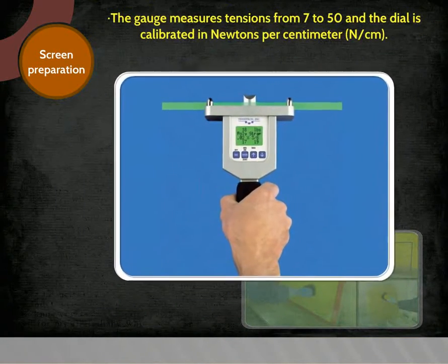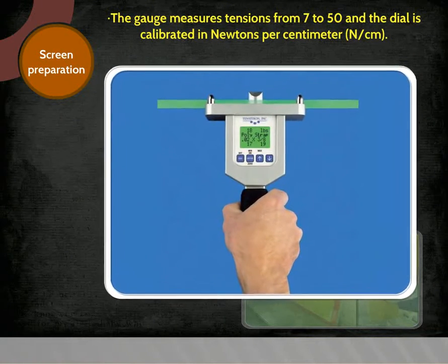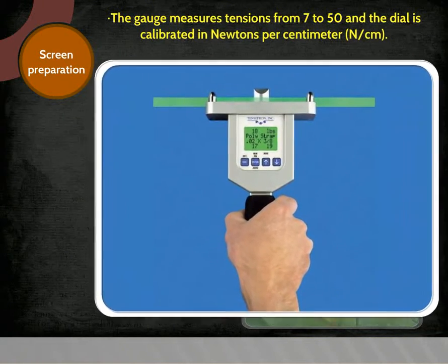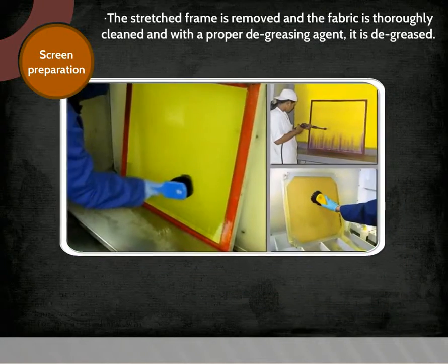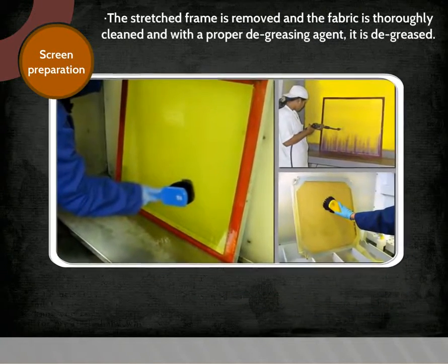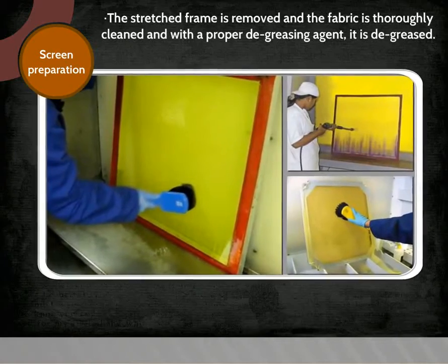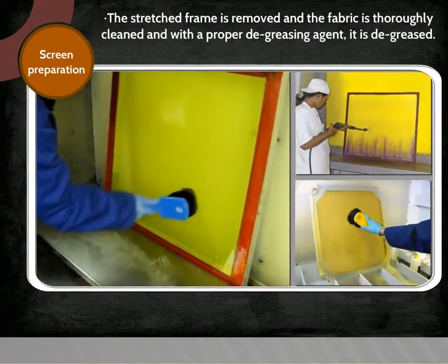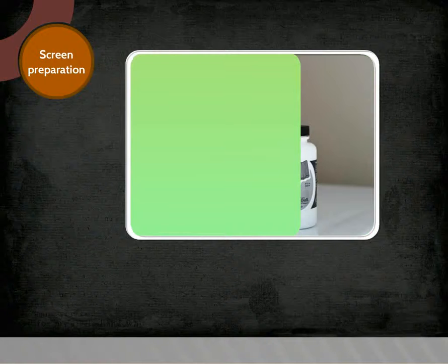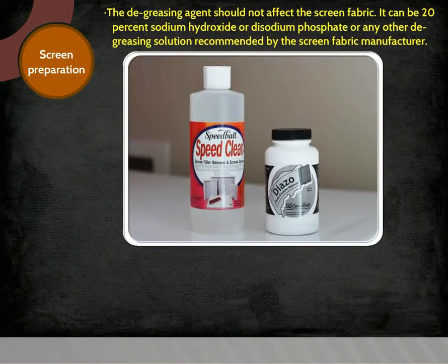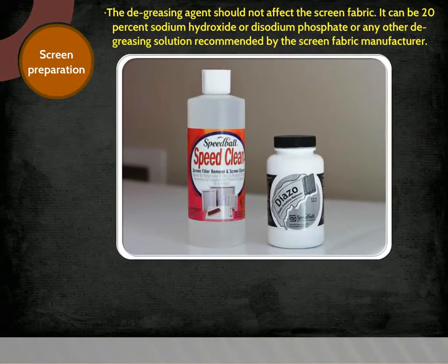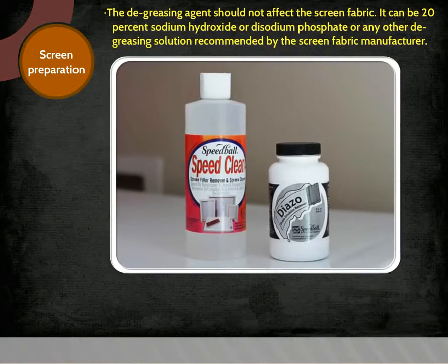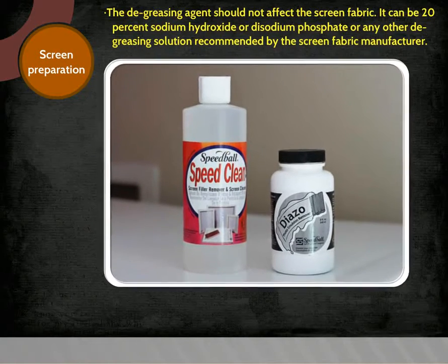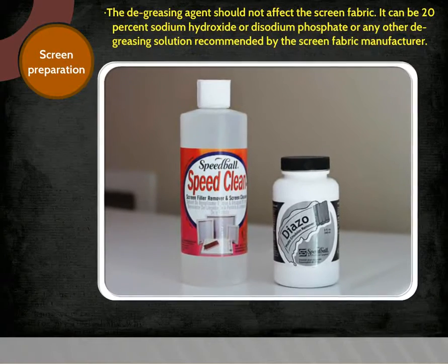The gauge measures tensions from 7 to 50 and the dial is calibrated in newtons per centimeter. The stretched frame is removed and the fabric is thoroughly cleaned, and with a proper degreasing agent it is degreased. The degreasing agent should not affect the screen fabric. It can be 20% sodium hydroxide or disodium phosphate or any other degreasing solution recommended by the screen fabric manufacturer.